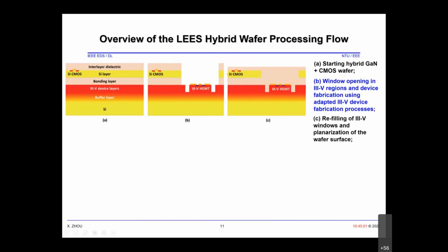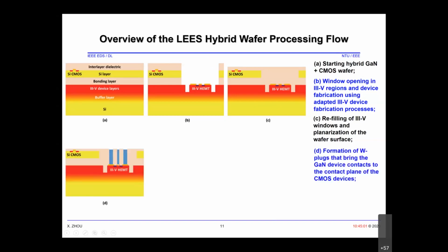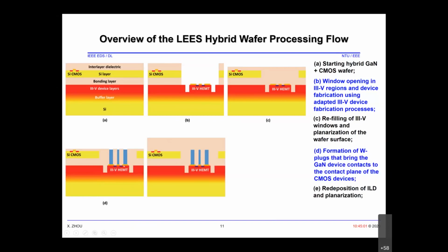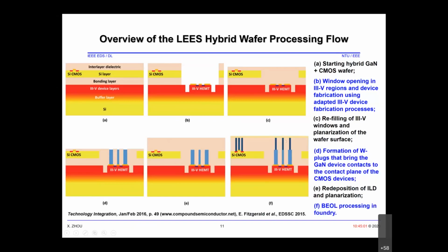Then we seal the wafer, refill the wafer with a planarization of the wafer surface. Then we do the tungsten plug to reach the III-V layers. Then redeposition of planarization. Then we do the interconnect between silicon and III-V devices. This can be side by side in the layout.